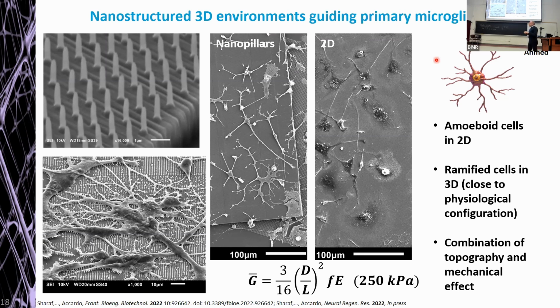And here we also have to stress the fact that this was the result not only of the effective shear modulus, but also of the employed topography. These are 200 nanometer diameter pillars, a dimension which is in the range of the dimension of the fibers which compose the extracellular matrix in the brain. So we could not disentangle these two, all right? So we think that both effects, topography and effective shear modulus, played a role in guiding the morphology of the microglia.